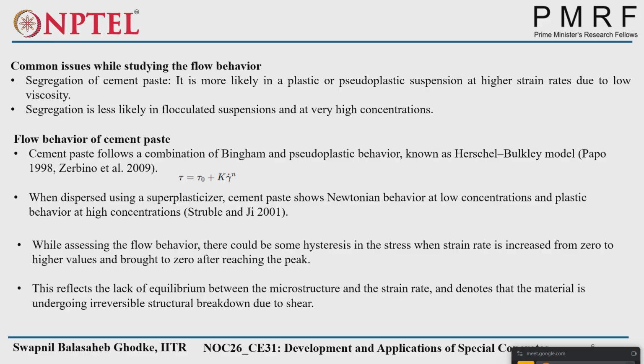If you see a simple example, not from the rheometer perspective, you have a certain cementitious mix or concrete mix, right? You mix it, you prepare it as some flowable or little bit workable concrete. Then you keep it for half an hour or 1 hour. A certain amount of setting will happen. Then you come back and put that material into the concrete drum or mixer. Again you mix it. Do you get the same flowability whatever we had at the time of preparation? Will you get it? No.